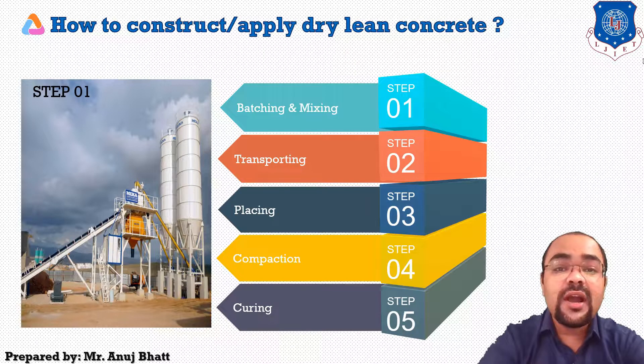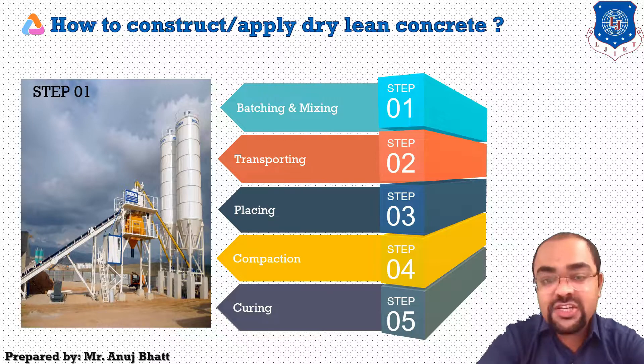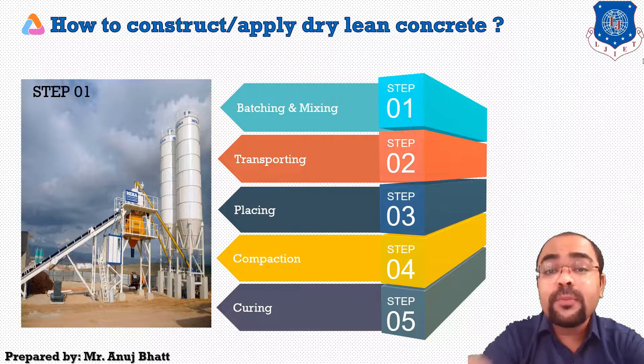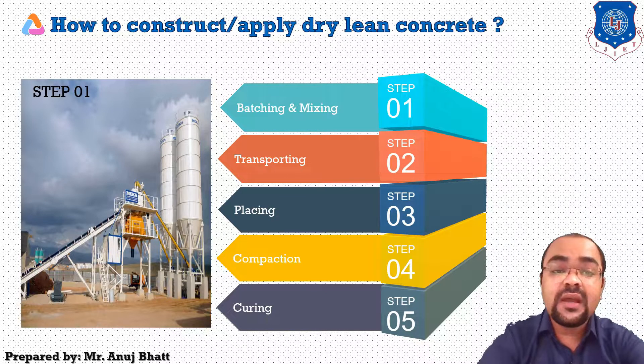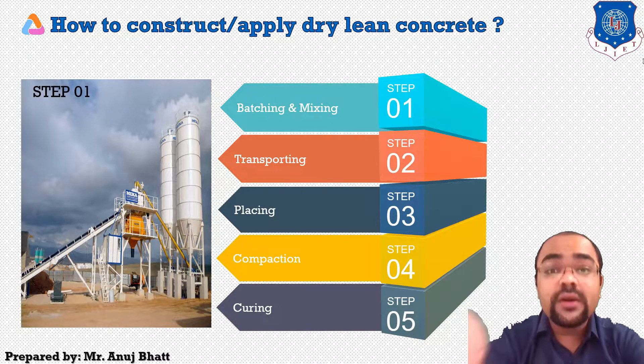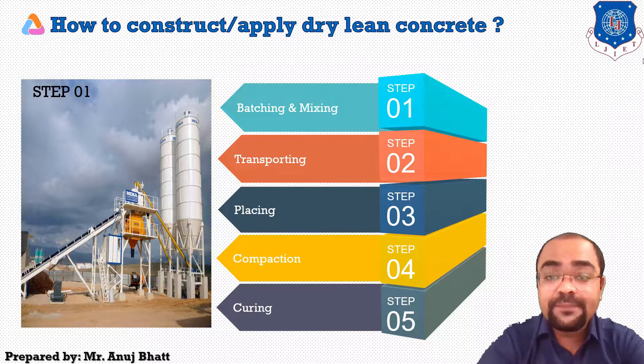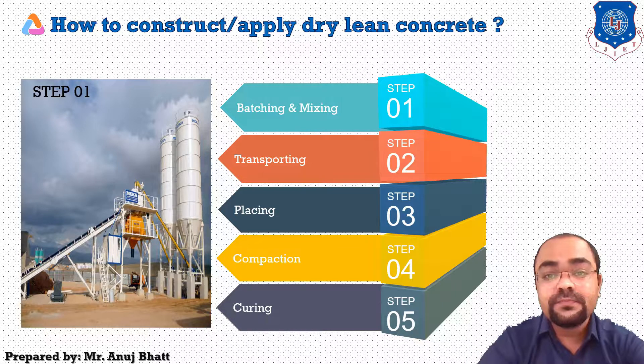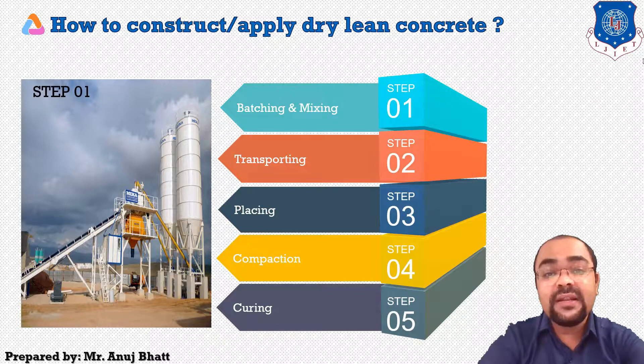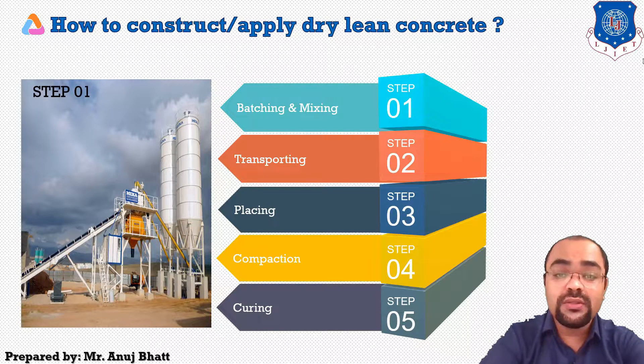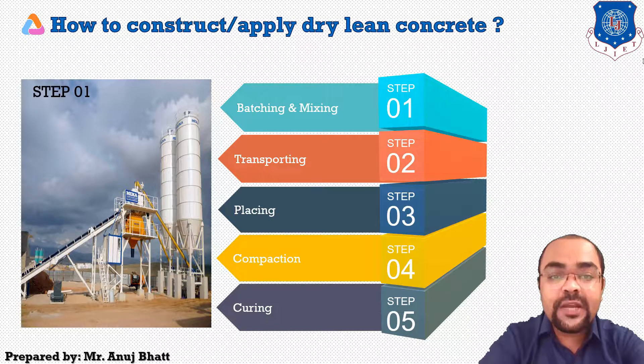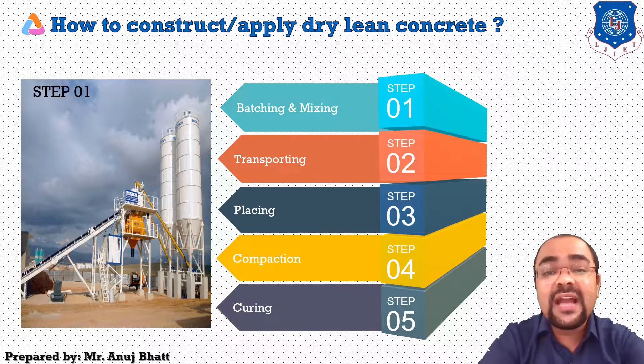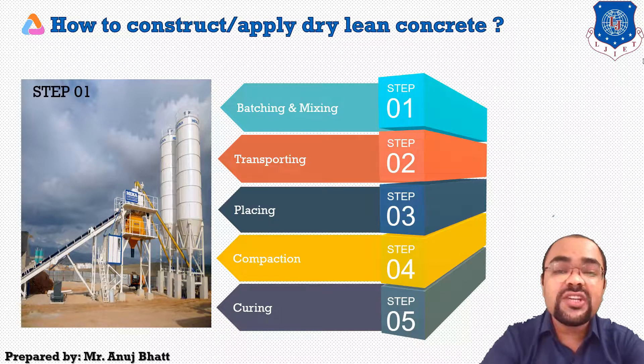The first step is batching and mixing. The batching plant shall be capable of separately proportioning each material by weight. As seen in the figure, two silos are used for storing the different materials. The capacity of the batching and mixing plant shall be at least 25% higher than the proposed capacity for the laying arrangements. Batching and mixing shall be carried out preferably in a forced-action central batching and mixing plant having automatic controls to ensure accurate proportioning and mixing. Calibration of the plant shall be carried out at regular intervals, normally each month.